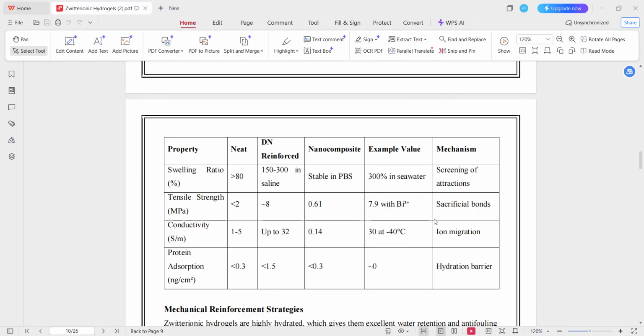Nanocomposite hydrogels display a stable swelling and moderate strength, for example, about 0.6 megapascal achieved through nanoparticle reinforcement. Conductivity improves from 1.5 Siemens per meter in neat gels to 32 Siemens per meter in double network systems, with reported values of 30 Siemens per meter even at minus 40 degrees Celsius due to the efficient ion migration. Importantly, protein adsorption remains extremely low in all the cases, typically below 1.5 nanogram per square centimeter and approaching zero, because the hydration barrier of Zwitterionic groups is preserved. Overall, the table highlights how reinforcement strategies enhance mechanical and transport properties while maintaining excellent antifouling performance.